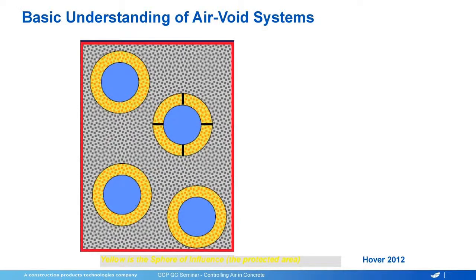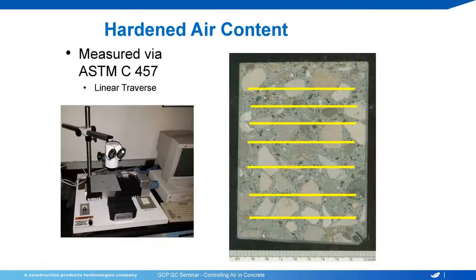Okay, so here we have these air voids again, and we're looking at some that are spaced out, not as much as we'd like. So we want to measure these, and the way we measure these with a microscope is the traditional way to do this, ASTM C457. And linear traverse just means that someone is reading this line and it's bubble on, bubble off when they see a bubble. So they're using that to both count the number of bubbles or the percentage of air, the spacing factor of the bubbles, and the size of the bubbles.